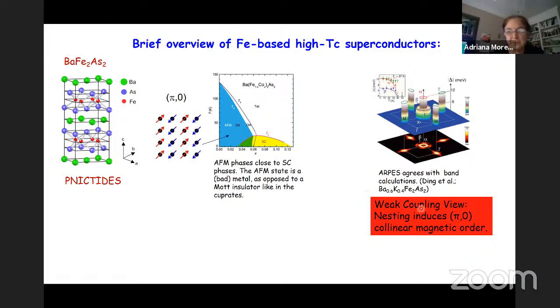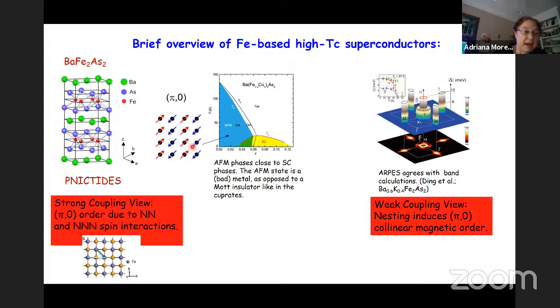That was the assumption, but at the same time, other people started studying the problem from the strong coupling regime. Although it wasn't very exact, they assumed the spins were localized, and looking at the structure of the lattice, they found that, for example, these are the irons. In order to hop to nearest neighbors from iron to iron, one has to go through the p orbital of the pnictide—so it was basically an overlap like that. And to go to the next nearest neighbor is also through the pnictide. So the resulting effective spin model had J prime and J of the same order, and because of that, it leads to a ground state with momentum pi0 in the magnetic order.